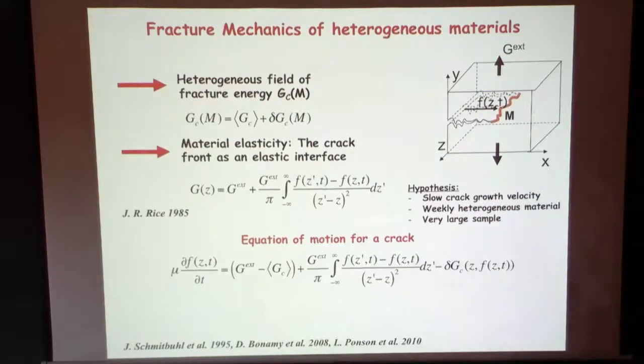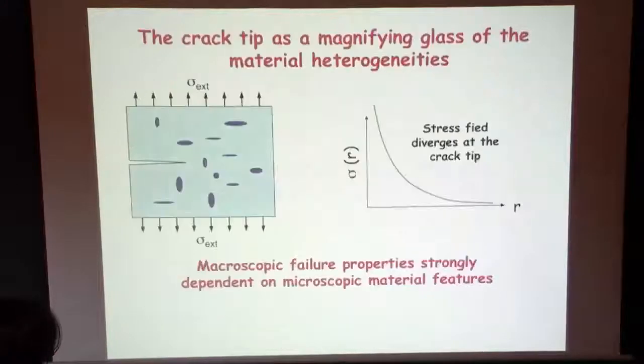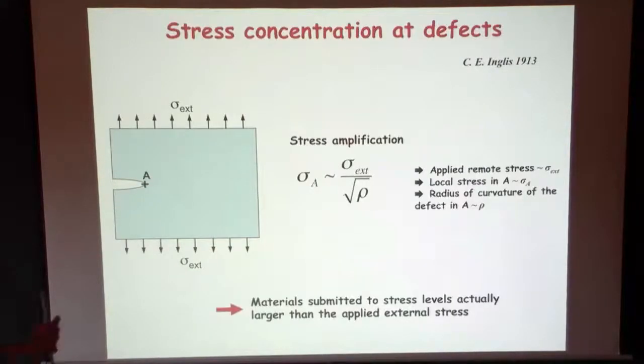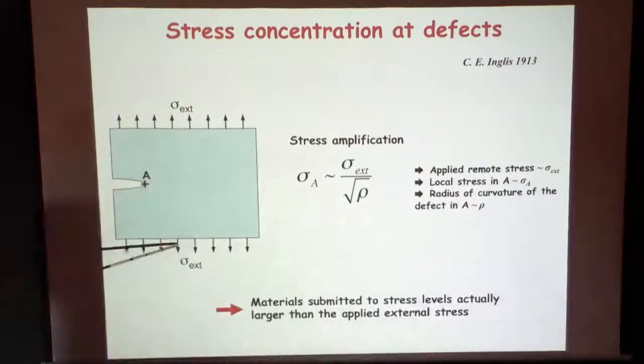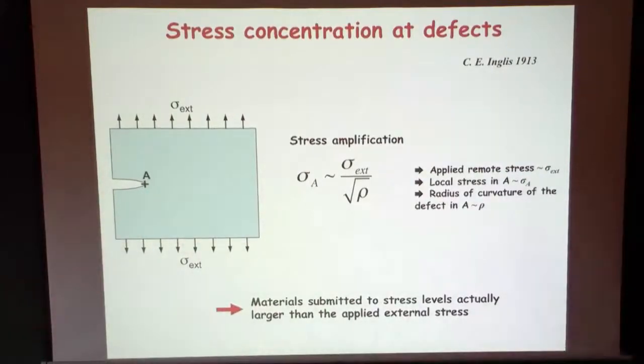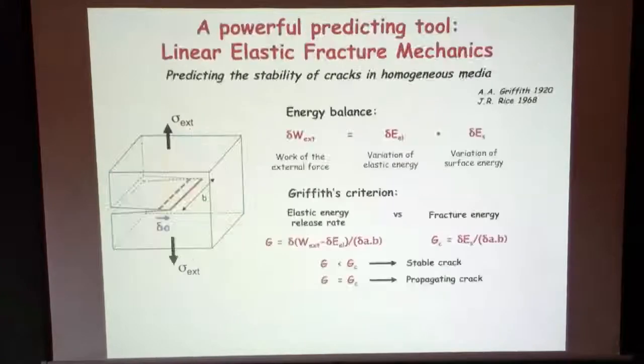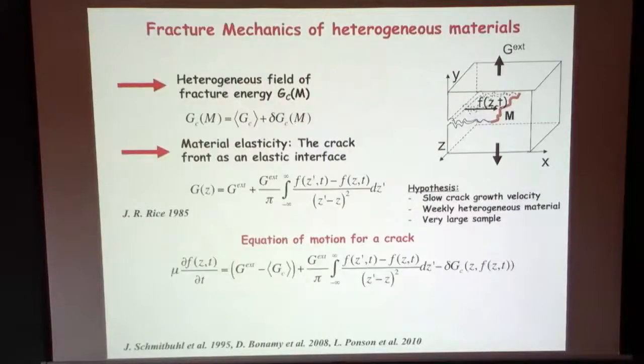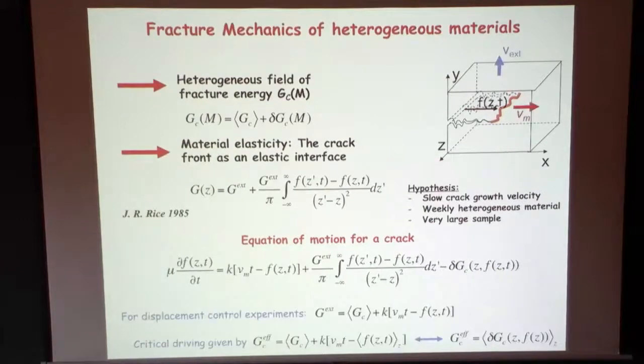We talk about the singular. Okay, if you start from this problem, for example, if you load this sample, since you don't have a stress singularity, you have to load it a lot before the crack actually starts. And when the crack starts, you have a lot of energy in your system that makes the crack accelerate. Yeah, but that elastic equation is implicitly assuming that you're minimizing the energy subject to the boundary condition of the crack. And that's only a valid approximation in the limit where it's quasi-static.